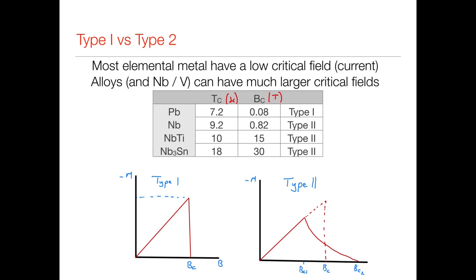What I've shown down here is how we expect a typical elemental superconductor to behave. As I increase the field across here, there will be screening currents which will perfectly cancel out the magnetic field. So the magnetization is the exact opposite of the applied field, so that inside there's no magnetic field. This is the perfect Meissner effect, a perfect diamagnet. And that happens all the way up to a critical field, at which point the material goes back to normal. So here we're superconducting and here we're normal. And so these type 1 materials typically cannot support very large magnetic fields.